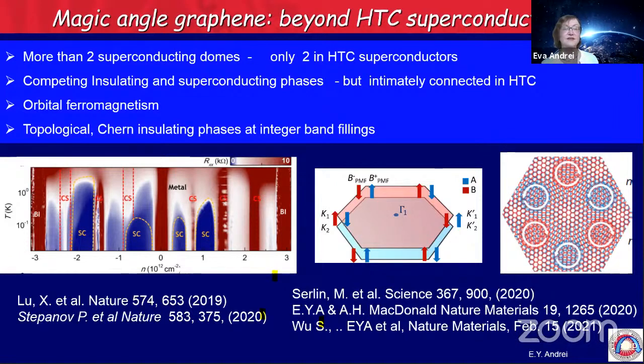Whereas in high temperature superconductors the insulating and superconducting phases are cooperating with each other, they are closely related, it turns out that in magic angle twisted graphene, they are competing with each other. So when we suppress the insulating behavior by screening the Coulomb interaction, the superconductivity is enhanced. Very different from high temperature superconductors. And when we put 3 electrons per Moiré, we get orbital ferromagnetism. We have a slew of topological properties, Chern insulating phases at integer band fillings. And you can see some of these references here. Some are ours that discuss these different aspects and how the physics of magic angle twisted bilayer graphene is different from that of high temperature superconductors. Whether it's going to teach us something about high temperature superconductivity, the jury is still out.